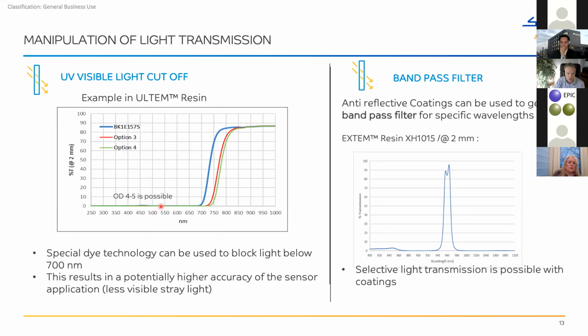So why is this important? Well, you can imagine if you have an infrared sensor that there's a lot of stray light from the sun, and you don't want to have that light interfering with the sensor accuracy. Of course, you can use a very expensive coating, but this is a much more cost-effective way to get this absorption of visible light. You can also use coatings for bandpass filters. So if you want to have, let's say, 960 nanometer VCSELs, and you want to have only transmission plus or minus 20 nanometers in that range and block all the other wavelengths, then that's something you can do with a coating. Of course, this is not so cheap to do, to be honest.